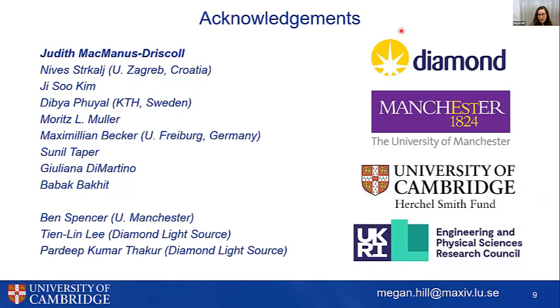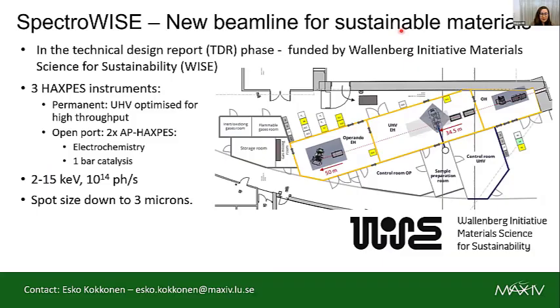And I do want to mention that now that I'm at MAX IV, I'm not doing HAXPES at the moment, but MAX IV is in the process of applying for funding and doing a technical design to get funding for a new beamline, which would hopefully be implemented in the next 5 years. It is a HAXPES beamline ranging from 2 to 15 keV, and using the 4th generation high flux of MAX IV could be really powerful, with a spot size down to 3 microns and 3 different HAXPES instruments, both for permanent UHV measurements and for more in situ and flexible ambient pressure measurements. And then I've put the contact down here if you are interested in this development and what you could possibly do here in the future.